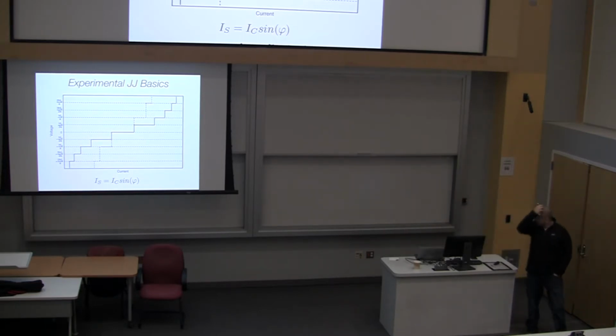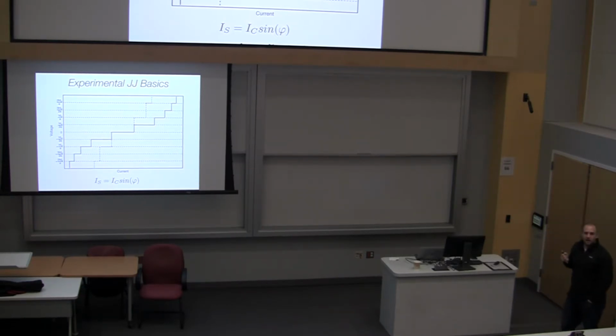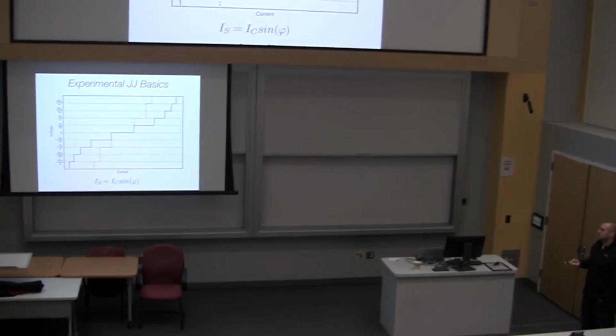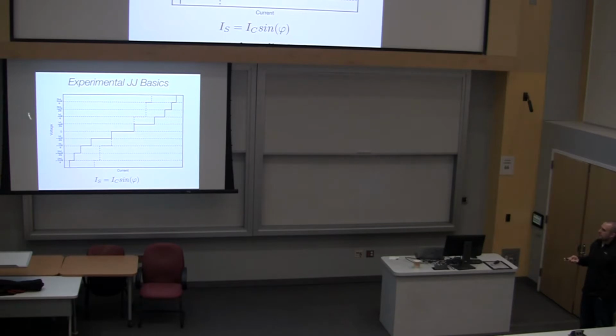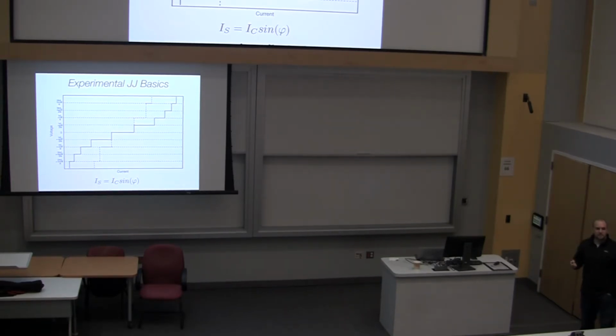The other thing is the experimental effects of the Shapiro steps, or driving these junctions with RF radiation. I said that if you can control the phase evolution, you should get steps in the DC voltage, because there's a regular progression of phase with respect to time. And so if I look at the DC voltage versus the current that I apply, I see steps in the voltage that I measure. These steps are determined by the frequency which you apply to the junction, i.e. how fast you move that thing up and down. So if I move it up and down faster, I would expect these steps to get higher. hf over 2e would be bigger.